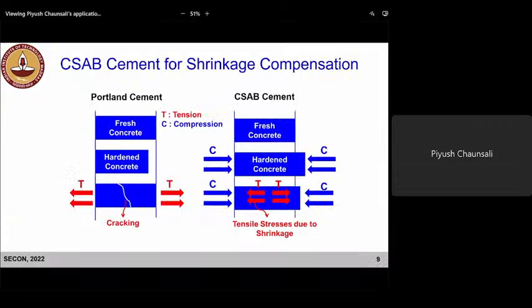Yeah. So I said that when we talked about the hydration reactions, few hydration reactions, when you are forming ettringite in presence of gypsum, and when you have both gypsum and portlandite, you have formation of ettringite. Those are expansive reactions. So first of all, when we talk about expansion, suddenly we don't feel comfortable. But here what we are doing is we are using this expansion to chemically pre-stress the concrete. So I will explain what we see here.